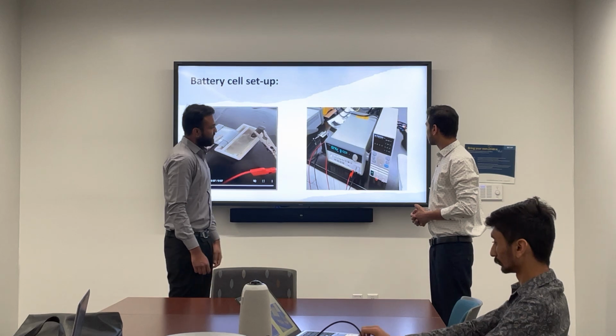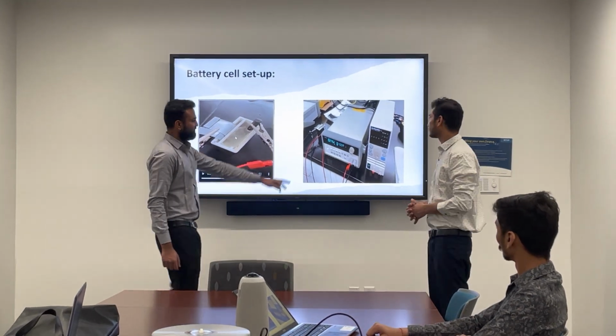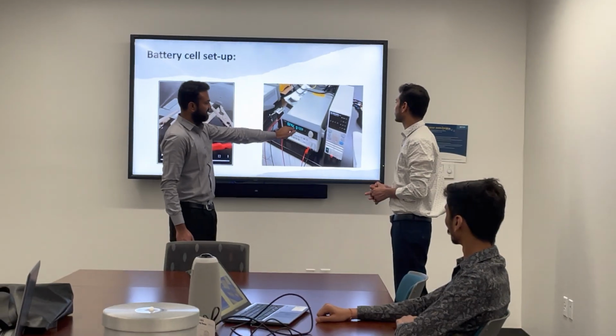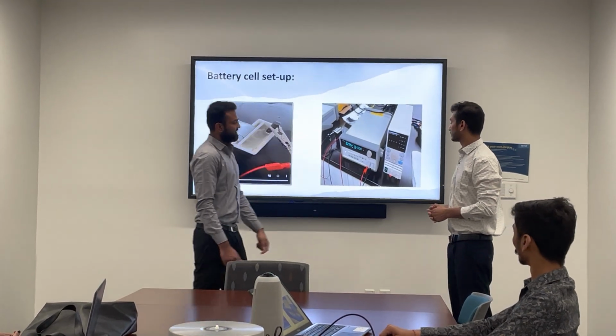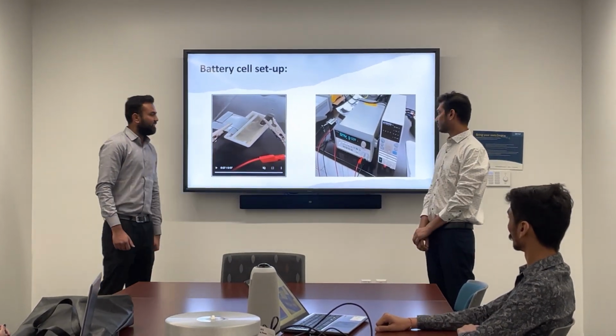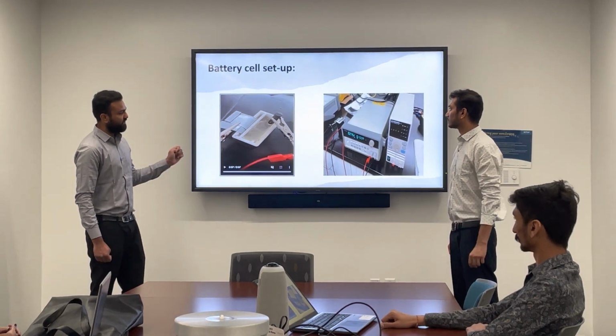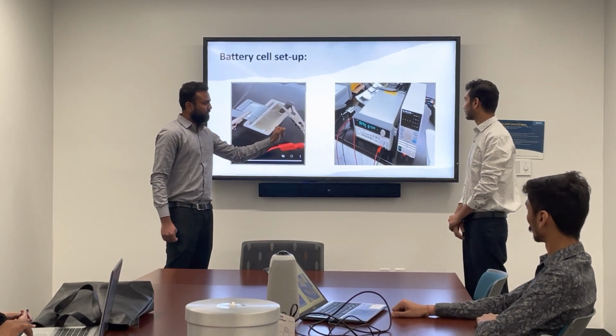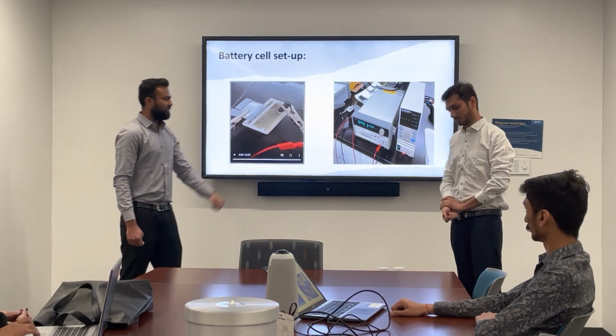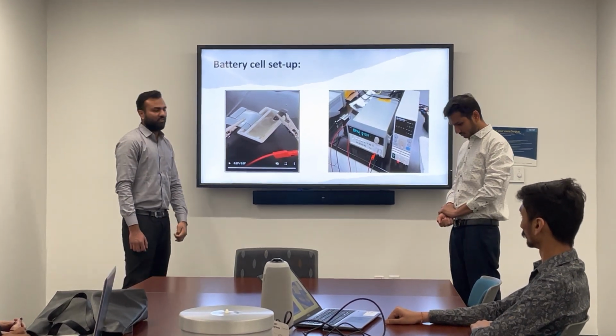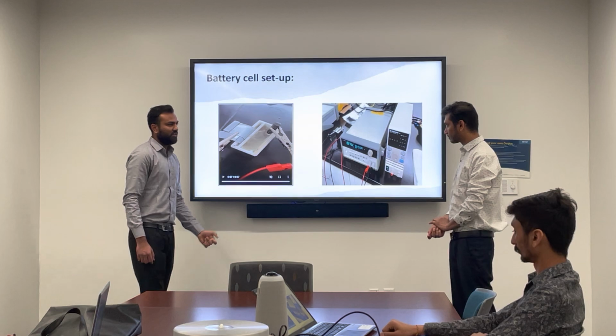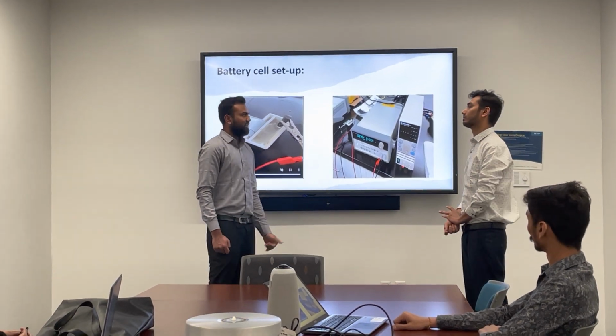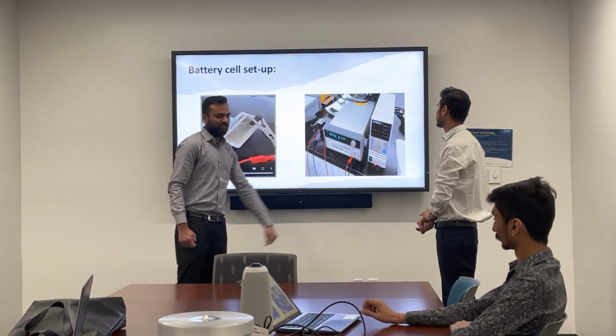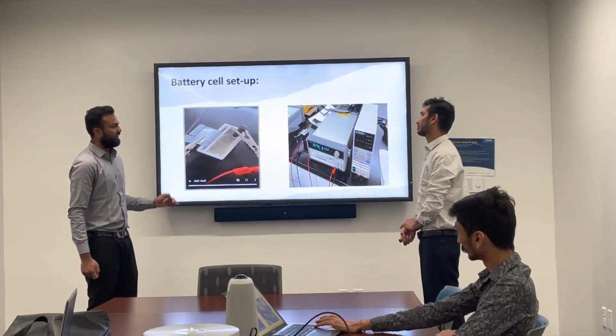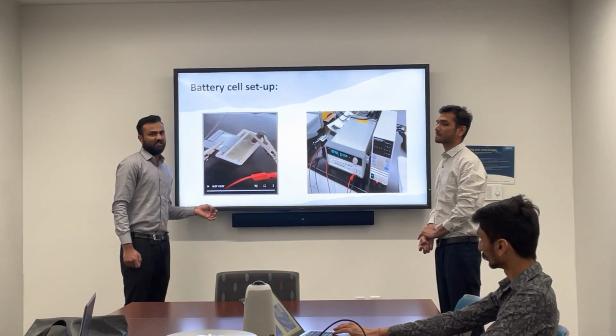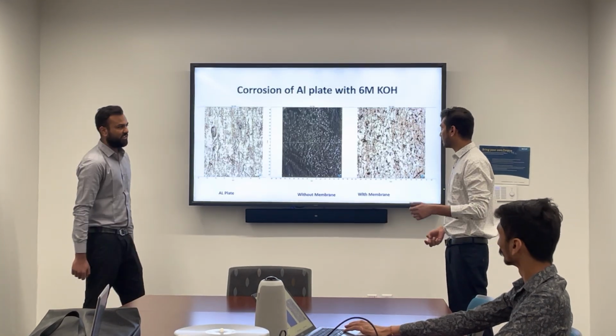The second picture shows the two devices that we used. The first one, which shows a number on display, is the charging device, and the other one is a discharging device. For the zinc-air battery and the aluminum-air battery, we used both devices. First we started with 2 molar concentration. We charged our battery for 15 minutes at 10 volt and 400 milliampere. Then we discharged using this device. We performed the same for 2 molar, 4 molar and 6 molar in the zinc-air battery as well as in the aluminum-air battery. Next slide please.